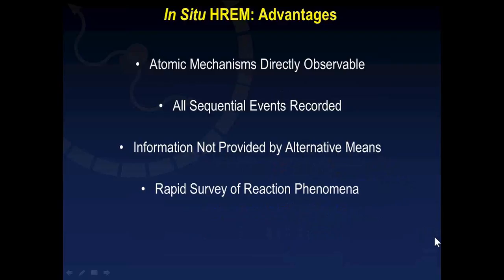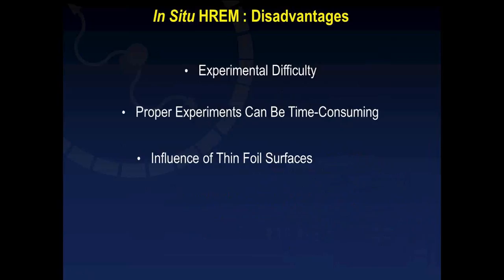Regarding the advantages of in situ high-resolution TEM: atomic mechanisms are directly observable, sequential events can be recorded, and the information obtained is not provided by alternative means. You can also conduct a rapid survey of the reaction phenomenon. Disadvantages include that experiments are always difficult and proper experiments can be time-consuming. There are also questions about the influence of thin foil surfaces, though in this era of nanomaterials — nanoparticles, nanowires, etc. — the large surface area to volume ratio is actually of interest to the community.